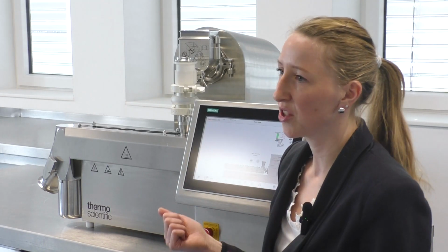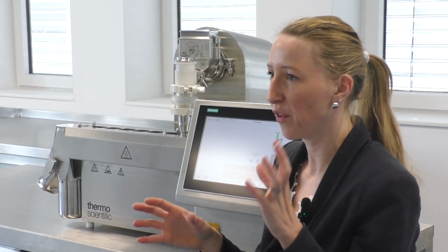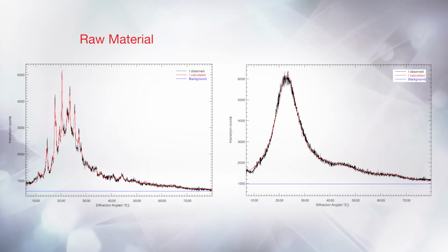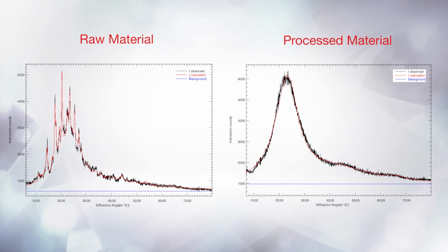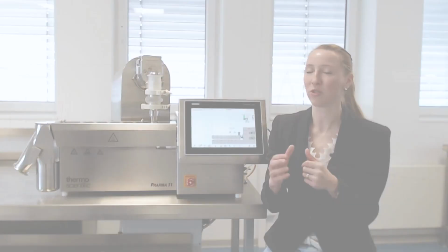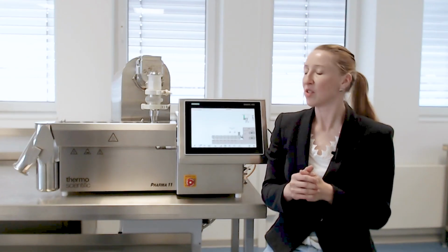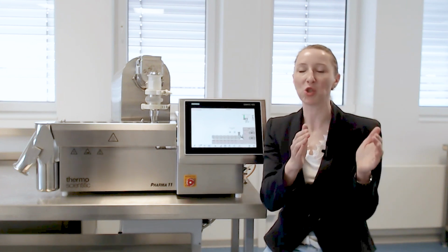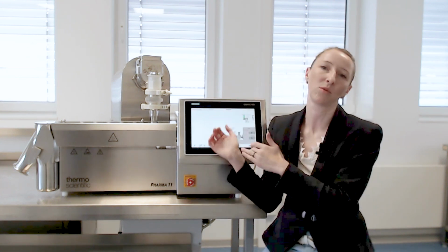And we really challenged that process. So we worked with a 50-50 blend. So 50% silica, 50% API. So if it was amorphous, we could really make a lot of drug amorphous. So this is quite a large amount of active ingredient. So with this, we could really be sure with this analytics, is this working?